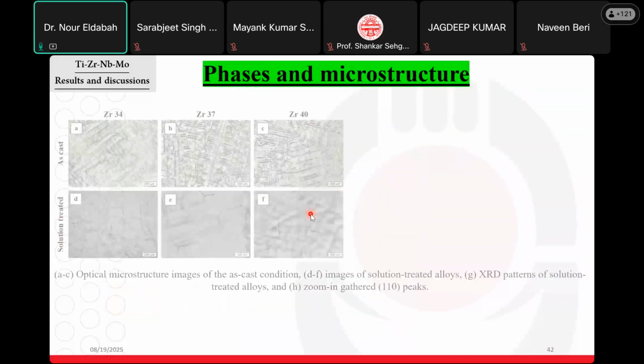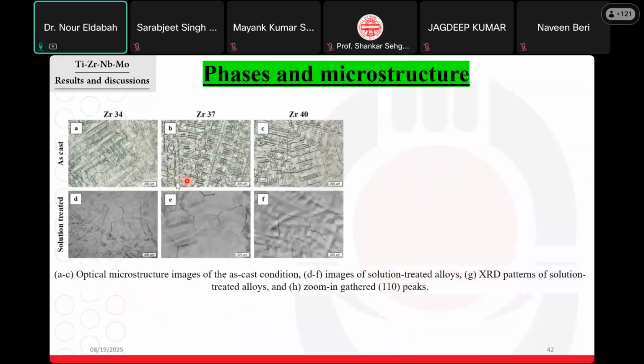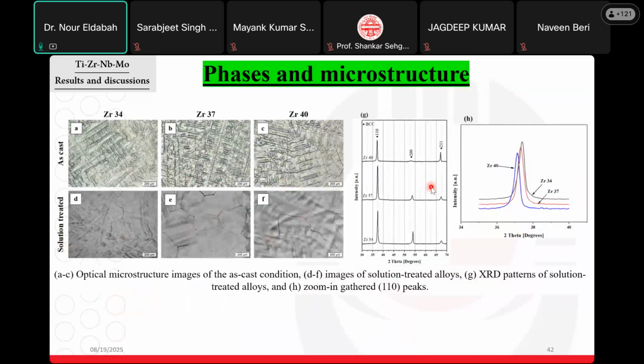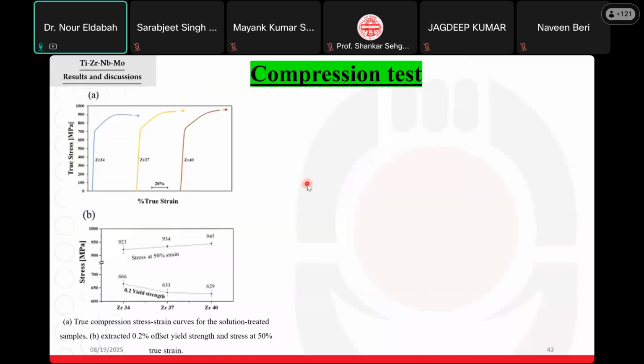As you can see, there is a minor amount of dendritic structure, and after solution treatment, the beta grains have appeared, and the XRD confirms the formation of a single BCC beta phase. Also, we accomplished the compression test. Yes, any questions?